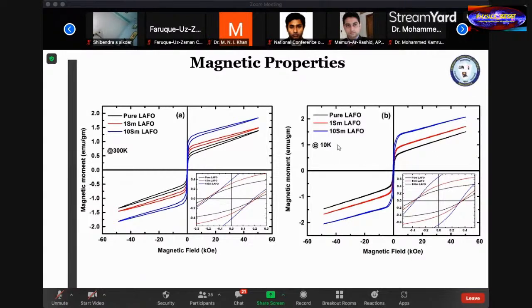From here we can say that magnetization of lanthanum ferrite mainly depends on the lanthanum 3+ and lanthanum 3+ interaction, iron 3+ and iron 3+ interaction, and lanthanum 3+ and iron 3+ interaction. So if we dope samarium, samarium 3+ and samarium 3+, and samarium 3+ and iron 3+ interaction can also take place.